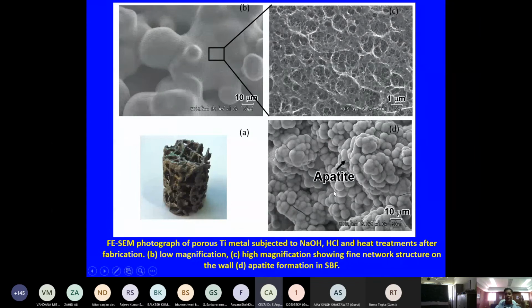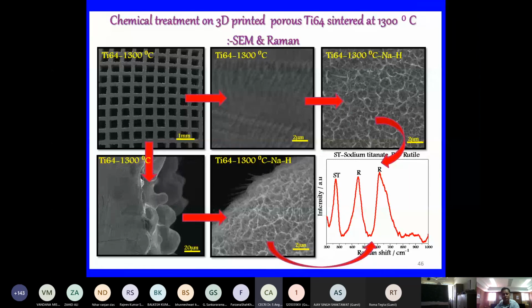so that the bone cell, if it goes inside, and you can see this is the apatite formation or bone formation when we soaked in simulated body fluid, you can see this calcium phosphate nodules have grown over the surface. This gives us an indication that if I make an implant and do this type of surface modification and go for animal study, in the same mechanism it will also form new bone, and that will help for better osteointegration or bone formation, and implant fixation will be more firm.